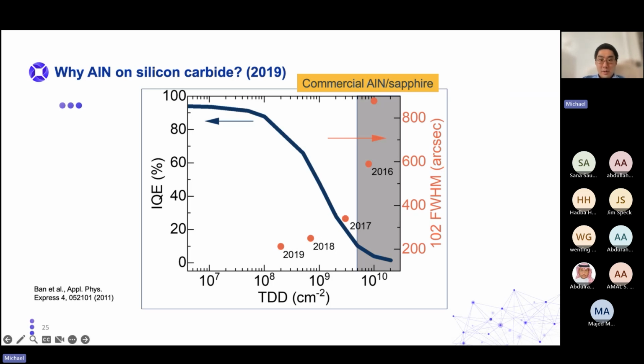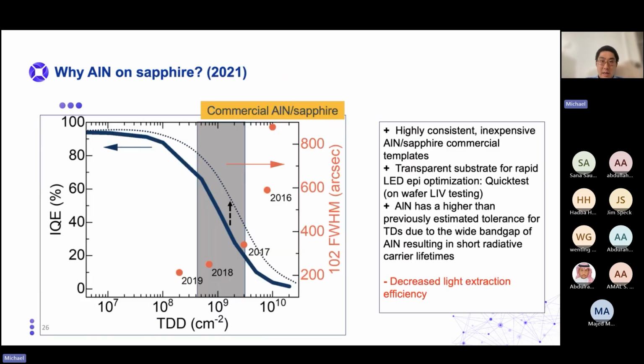So our silicon carbide work is one order of magnitude better than the best aluminum nitride on sapphire in 2019, and 2 orders of magnitude better than the average aluminum nitride on sapphire in 2019. However, in 2021, there was a big breakthrough in aluminum nitride on sapphire templates with high temperature face-to-face annealing. Aluminum nitride is first deposited on sapphire through, for example, sputtering, MOCVD, HVPE, all these different processes, it doesn't really matter, and then annealed at around 1700 degrees Celsius. That decreases the defect density by basically an order of magnitude.